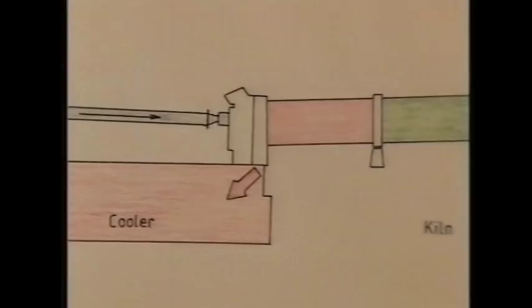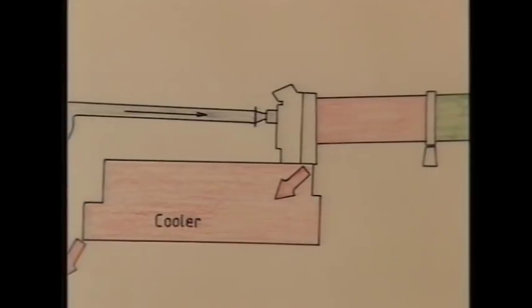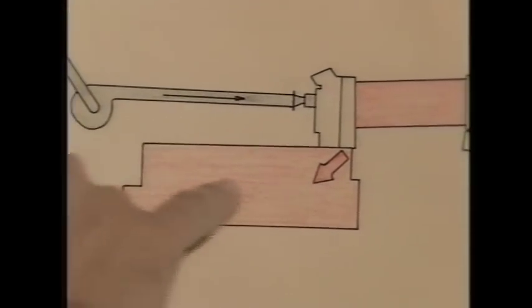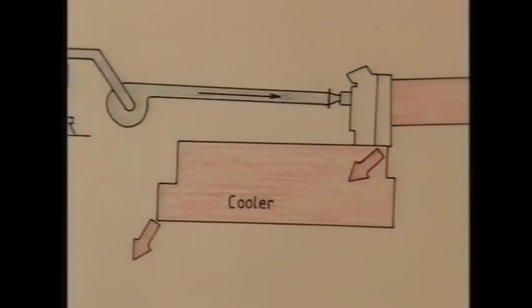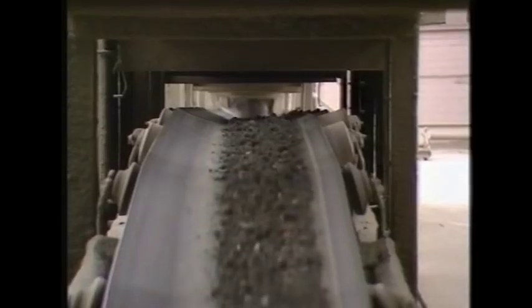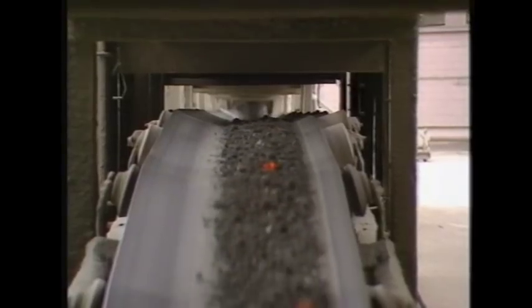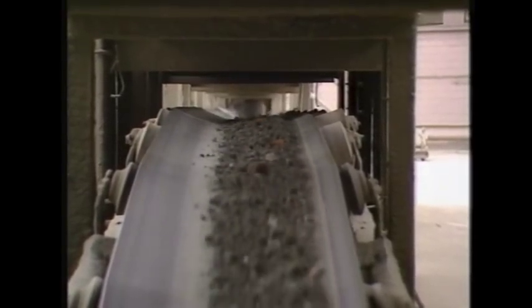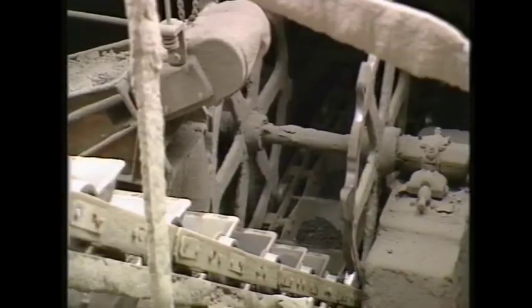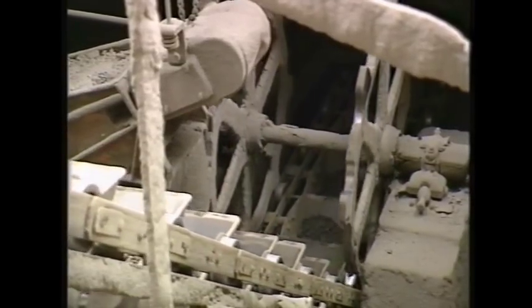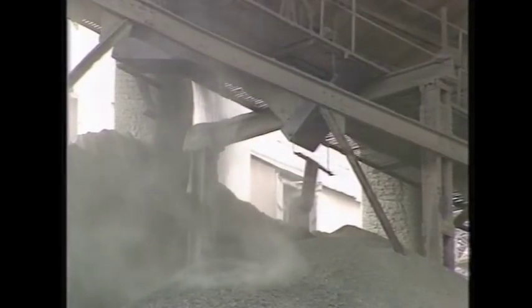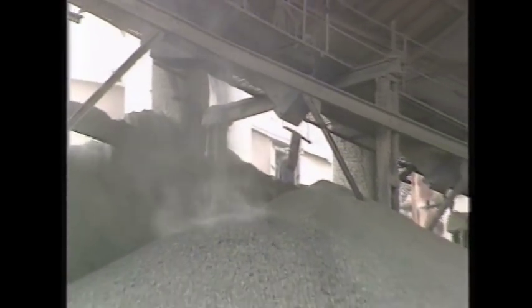Product from the kiln is known as clinker. The clinker then drops into a moving grate cooler where it is cooled for ease of handling. Again, this material is tested every hour by our laboratory mix controller, and that is put into a large clinker storage shed, the positioning of the clinker depending upon the outcome of the chemical test.